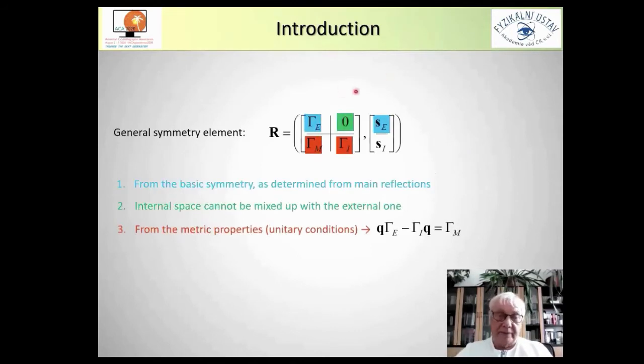As mentioned in previous slides, we are working now in superspace where the symmetry is described by matrices which are 3+d by 3+d. However, for description of modulated structures, there are some strict restrictions which make this description in higher dimensional space easier. First of all, if we are taking only main reflections, we can derive the symmetry of this 3 by 3 matrix and translation part only from main reflections.